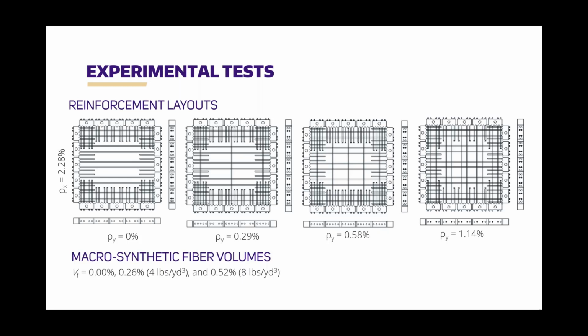So here's what that looks like in terms of the reinforcement layout. You can see in all cases the steel that's going from left to right horizontally is the same in all sets of the panels, and really all we're varying then is the reinforcement in the vertical direction. So the specimens with 0.29% had 3 bars, with 0.58% had 5 bars, and with 1.14% had 10 bars crossing the test region. And the test region is really that portion that's in the middle of the panel there, once you get past those headed bars that are there to help anchor in these rigid blocks. And those rigid blocks are there to allow us to attach it to the test machine and apply those shear forces.